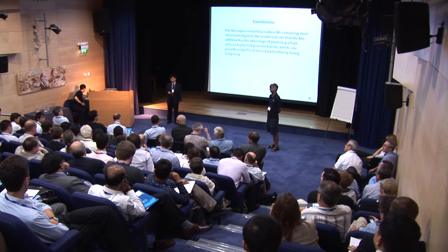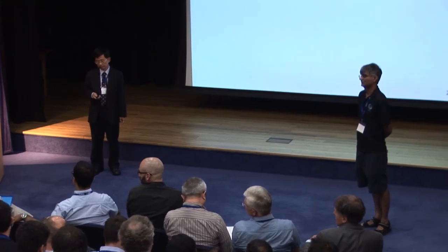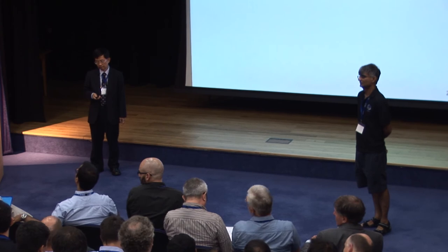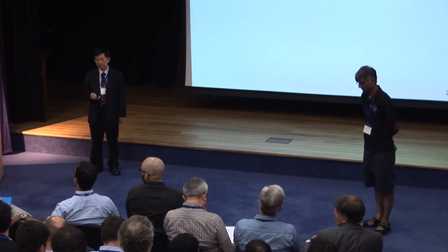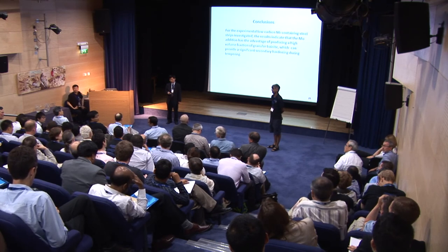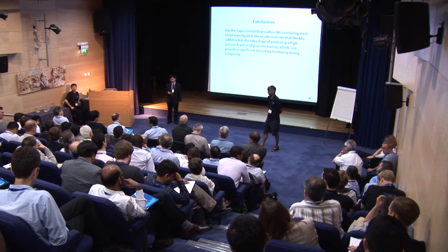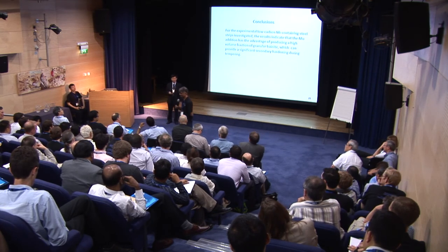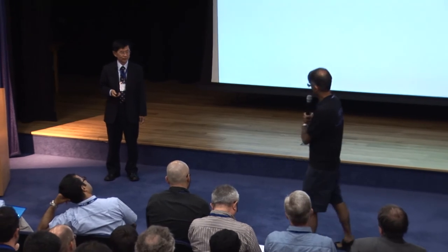In the titanium molybdenum carbide, we found that some addition of the molybdenum in the titanium carbide will relax the interface strain energy between the ferrite and the titanium carbide. But it is not clear that the same mechanism controls the molybdenum accommodation in the niobium carbide. I think the chemical analysis here is quite interesting, of the carbide.